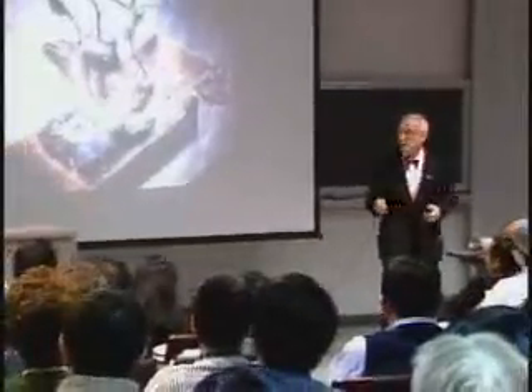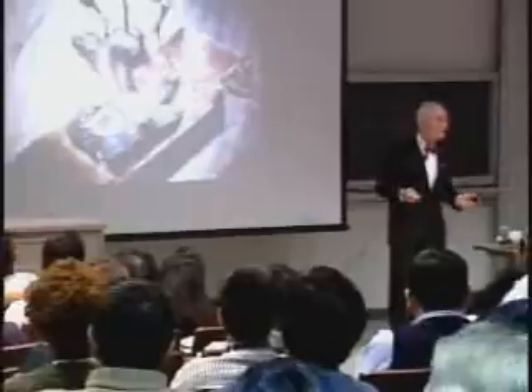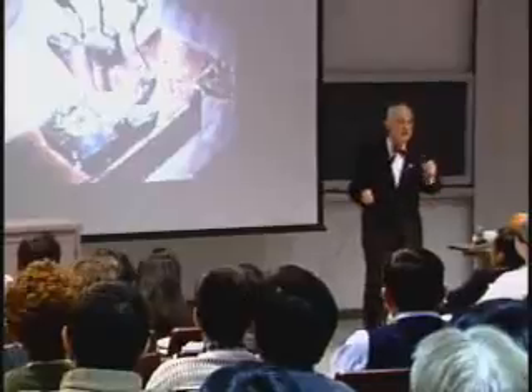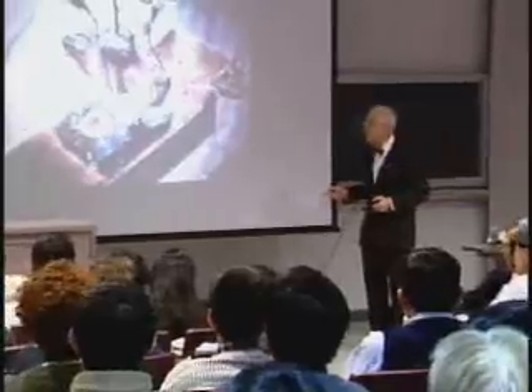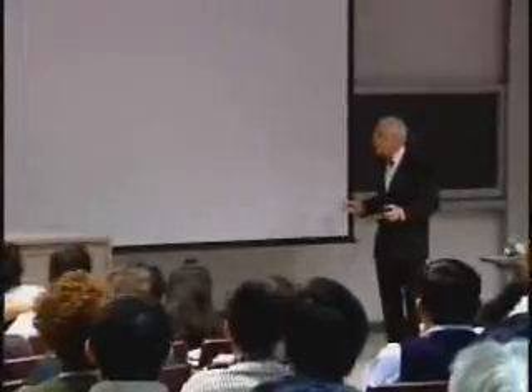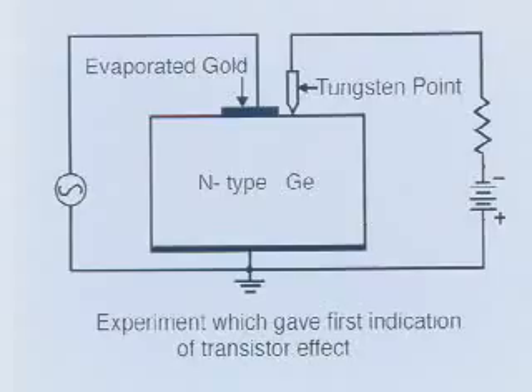John told me that Walter had an accident or something and it didn't work. But I think that as I look at this diagram in greater detail now, with the advantage of time and further knowledge, they had a grain boundary here. This was polycrystalline material. You didn't have good single crystalline material. And so you don't throw this experiment away. They moved the tungsten point from here. They moved it out to the edge, and they did their experiment. In other words, here was the gold. They took the point contact from inside of here where it should have been. They moved it to the edge, and Walter got some kind of gain, some kind of effect.